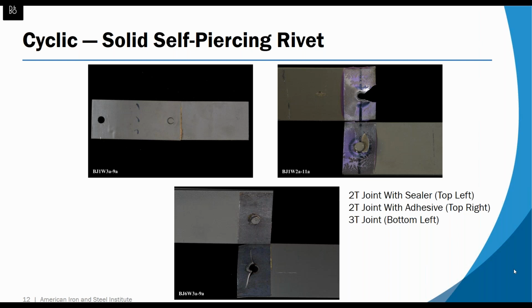These are the same 3 joints in cyclic fatigue, and here we see some differences from the baseline. I will preface this by saying the way we developed the loading for the cyclic fatigue was we tested the baseline resistant spot weld joints and found out what level of cyclic stress would cause a failure in that joint in approximately 100,000 cycles, and we set that across all joining methods for that joint. So at the stress level that produced a failure at 100,000 cycles for resistant spot weld, in this case, the solid self-pierce rivet plus aluminum sheet and sealer actually didn't fail at 100,000 cycles and went out to a 1,000,000 cycle run out without failing.